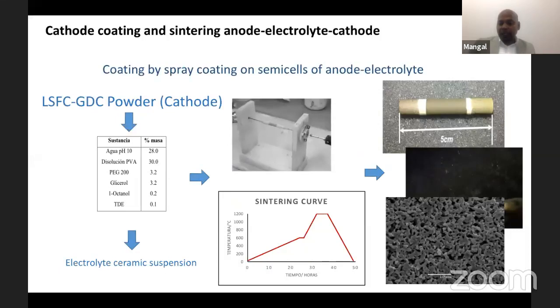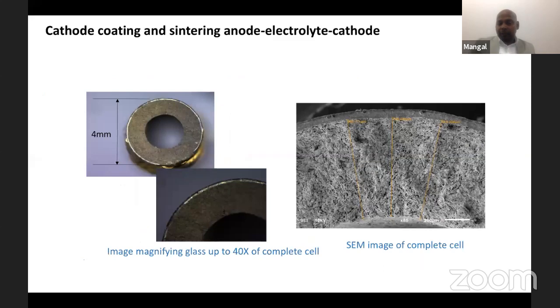But if you see the cross section of the tube, you can see it's around 4 millimeter, and in the thickness you can see maximum 1000 microns. In the majority, you can see the anode tube around 800 to 900 microns. So the rest, 100 to 120 microns, has to have an anode, electrolyte and cathode. So this is the cross section.